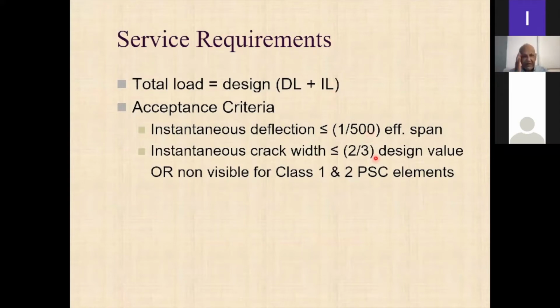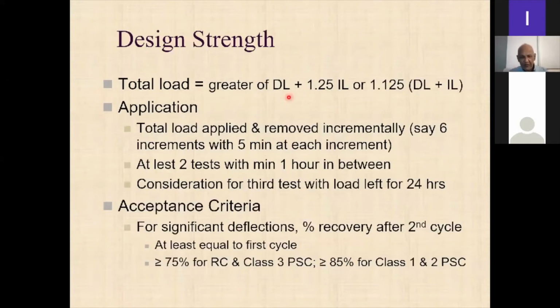If you want to get the design strength, then you use dead load plus 1.25 of imposed load, or 1.125 of dead load plus imposed load, right? So you apply the load and remove it incrementally. You have to do 2 tests with one hour in between, and you can consider even doing a third test with the load left for 24 hours.